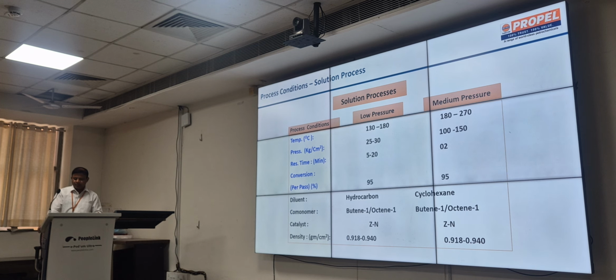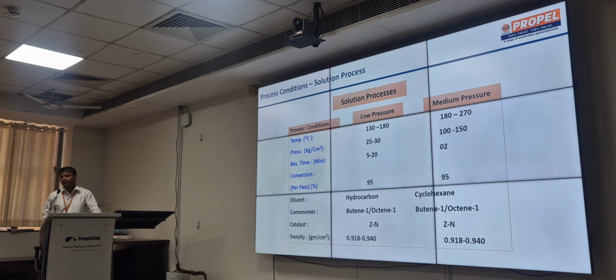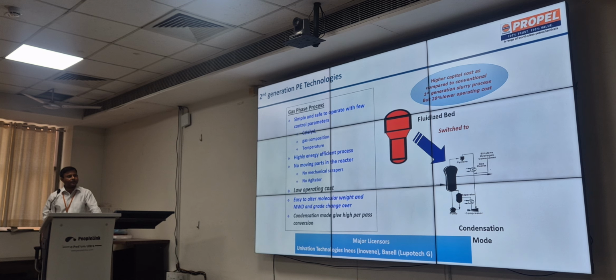Solution process, low pressure and medium pressure: 180 to 270 degrees centigrade as the temperature in the medium pressure, and 130 to 180 in low pressure. Residence times are 5 to 20 minutes in low pressure and 2 minutes in medium pressure. Per pass conversion is the same, 95%. Cyclohexane is mostly used as the solvent. The density range is similar, but the only drawbacks are the cyclohexane solvent we are using and that high molecular weight cannot be obtained in the solution process.